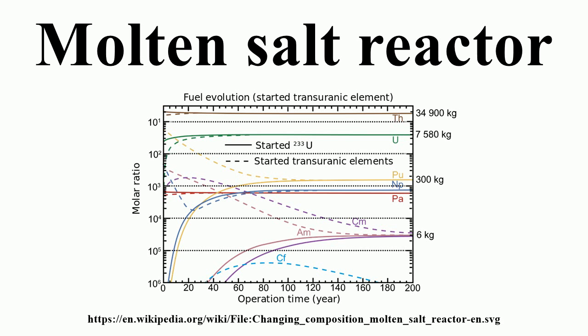Molten salt reactor experiment. Oak Ridge National Laboratory took the lead in researching the MSR through the 1960s, and much of their work culminated with the molten salt reactor experiment. The MSRE was a 7.4 MWth test reactor simulating the neutronic kernel of a type of epithermal thorium molten salt breeder reactor called the liquid fluoride thorium reactor. The large, expensive breeding blanket of thorium salt was omitted in favor of neutron measurements. The MSRE was located at ORNL. Its piping, core vat and structural components were made from Hastelloy-N and its moderator was pyrolytic graphite. It went critical in 1965 and ran for 4 years.